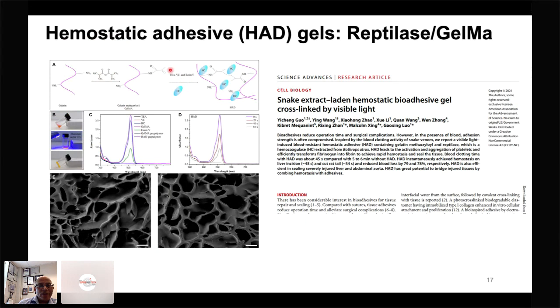And then we have used triethanolamine, vinylcaprolactam, and then eosin Y, which is a visible light activated initiator for cross-linking. And we took then an enzyme from a venomous snake, and this enzyme is reptilase, basically an enzyme that is extracted from the snake. And then we embedded, we loaded that, and that paper came out about 6 months ago, in this title. It's published in Science Advances.